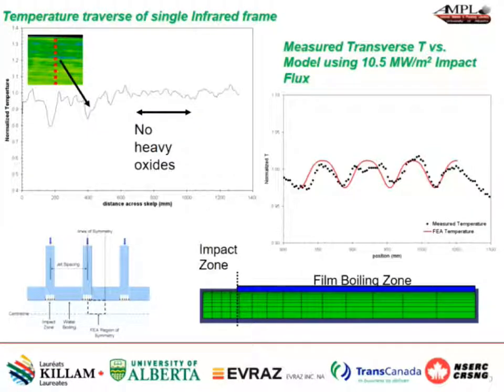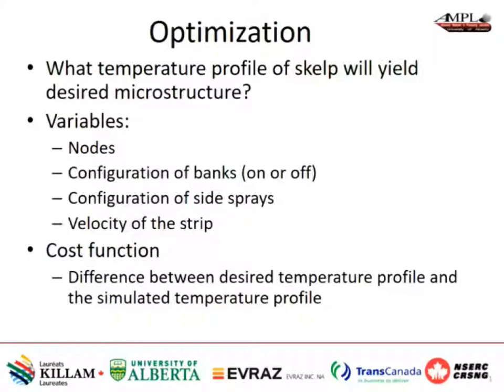But what is the impact zone heat transfer coefficient? We basically did the experiments to get the temperatures and then varied this impact zone heat flux until we got very good matching with the measured temperature profiles. And why this is fluctuating like this is because these zones here, when it's low, is where an impact zone column of water is hitting the surface of the scalp. So having this heat flow model, the question becomes, how do you make sure you can turn these banks of water along the runout table on and off? How do you control that, and that's how you control the cooling rate.